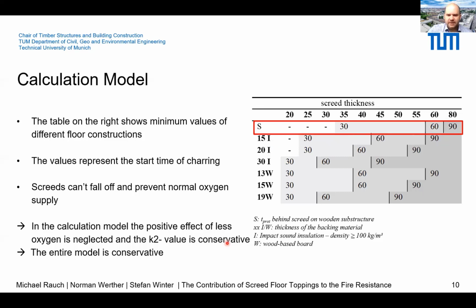The protective effect of screeds after reaching the temperature criteria of 270 degrees is considered by the K2 factor. The positive effect of the lack of oxygen is neglected in the calculation model. And so the K2 value represents a conservative result. These assumptions done in the study lead to a conservative model compared to the test results.